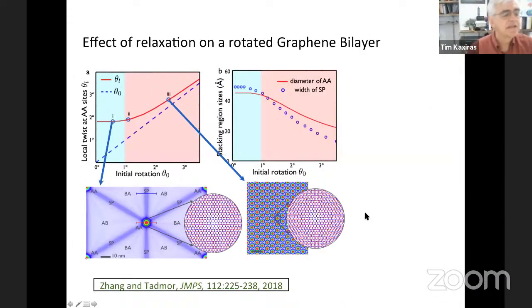So here's a slightly more detailed view of two key features of this relaxation. The horizontal axis in both of these plots is the initial rotation, how much rotation you impose on the two different graphene layers. And the first plot is a picture of the local twist, the additional local twist that I mentioned. So if you go to large angles, about 2-3 degrees or so, theta l basically is proportional to the initial rotation. And if you go to smaller twist angles, the local twist flattens and becomes constant.